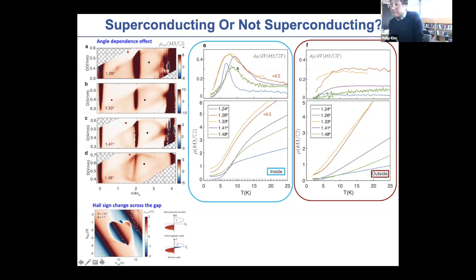Thanks. So basically, just one sample out of say 5 or 6 samples that we tried shows this so-called zero resistive behavior. Now we are really pushing the limits: can we really claim superconductivity based on one sample and only zero resistance? I think this is equally applicable to many other 2D systems. For the magic angle twisted bilayer, there is a lot of growing evidence that superconductivity is indeed observed in many different samples, including the phase coherence behavior.